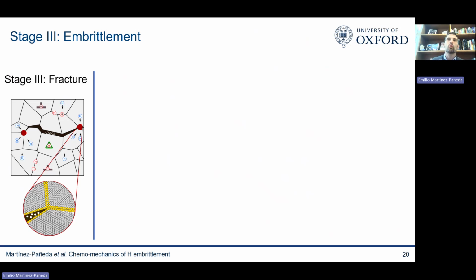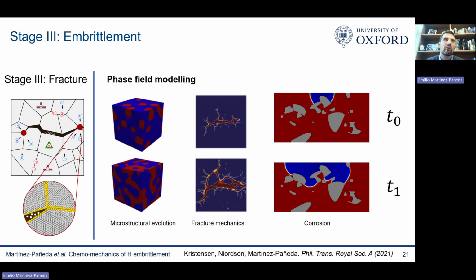You need a tool that allows you to simulate how cracks evolve. Cracks are discontinuities, interfaces - we don't like discontinuities, we like things to be smooth. We need to capture how this discontinuity evolves, combined with all the chemomechanics or electrochemomechanics I showed before, like moving boundary conditions and so on. So that's a challenge, and what has worked very well for us is phase field models.